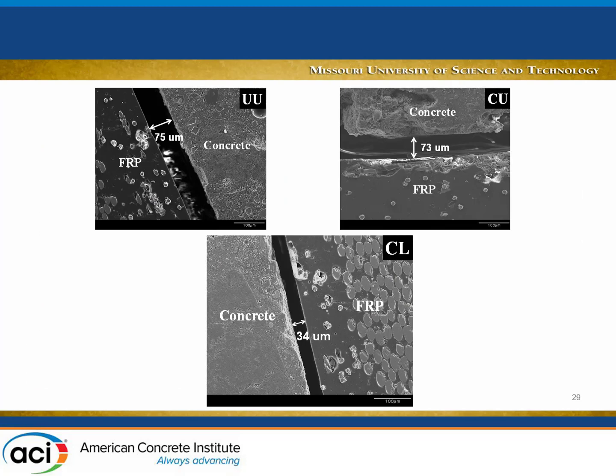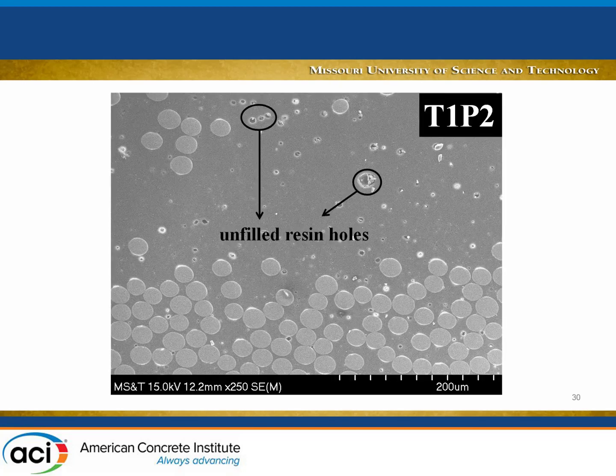Over here we did the SEM analysis for the specimens. Those two are the ones without loading. For example, here this is the FRP side, this is the concrete. You see there is a difference here of 75 microns. This is probably due to shrinkage of the concrete. Whenever we apply the load, this gap, and this is consistent, I'm here presenting just a sample. When we apply the sustained load, this gap, the gap between the concrete and the FRP, is close to 34 microns. This is probably due to the dilation of the concrete under the sustained load.